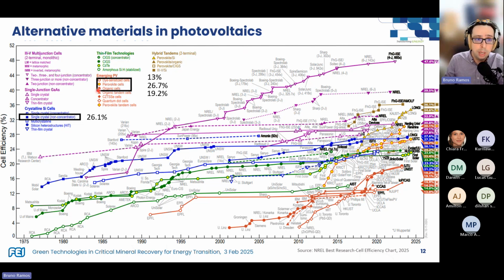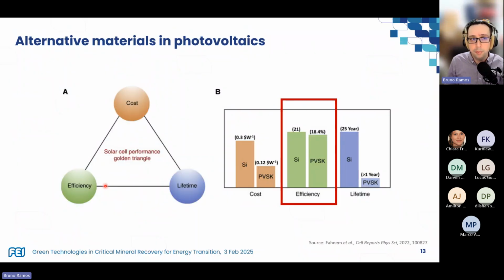And if we look at the three that I just mentioned before, we have the dye-sensitized cells at 13%. The perovskite cells, what I mentioned two slides before, at 26.7, and the organic cells are already reaching 19.2. So the perovskite cells already have a higher efficiency reported, experimentally achieved, right? Higher than the single crystal silicon cells. But of course, that's not everything, right?